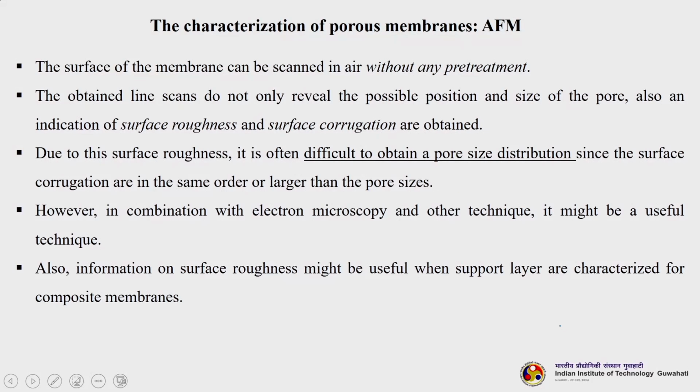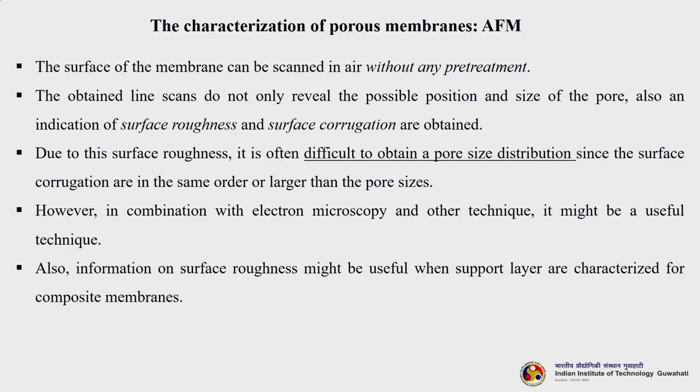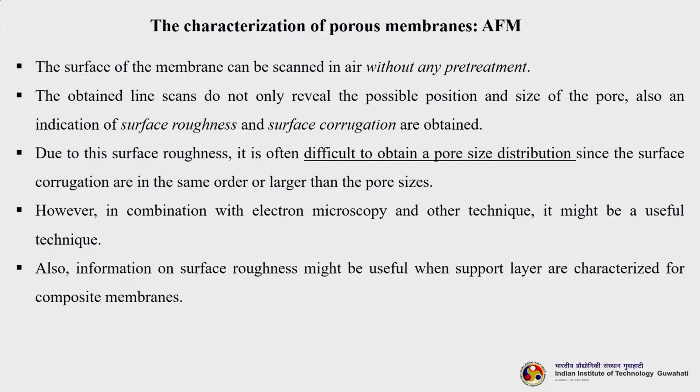The surface of the membrane can be scanned in air without any pretreatment. This is another advantage of the AFM. The obtained line scans do not really reveal the position and size of the pores, but they give an indication of surface roughness and surface corrugation. So, AFM is the only technique which will give us an indication of surface roughness. Due to this surface roughness, it is often difficult to obtain a pore size distribution. So, PSD or pore size distribution is a bit difficult to get in the case of AFM, which is very easy to do in the case of SEM. However, in combination with electron microscopy and other techniques, it might be a useful technique.